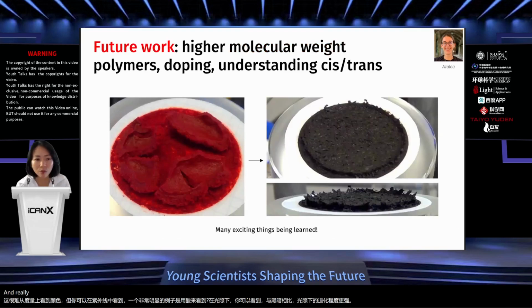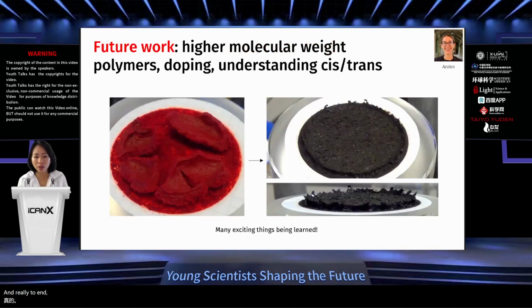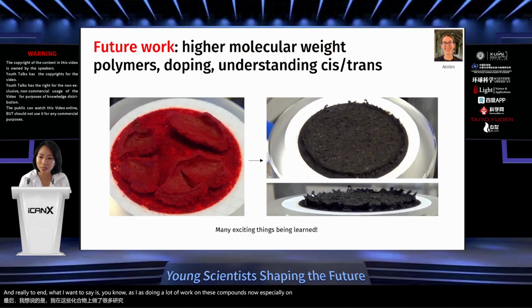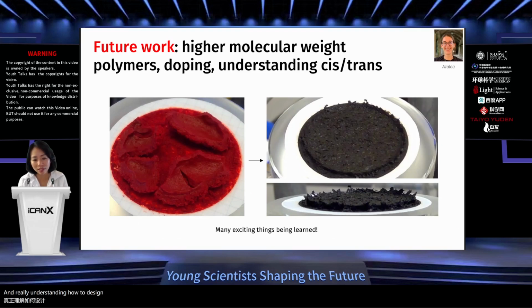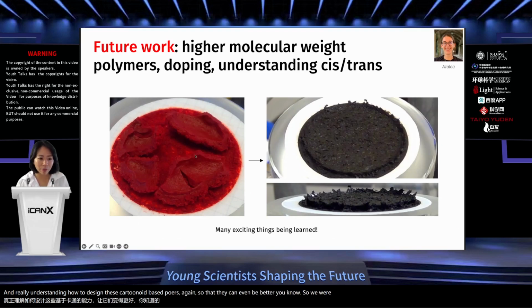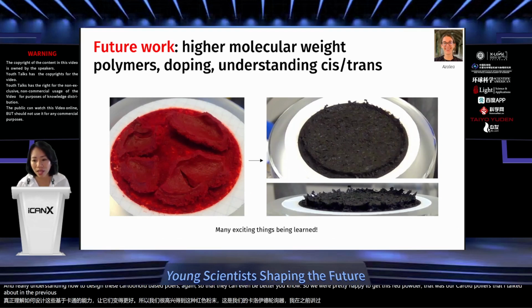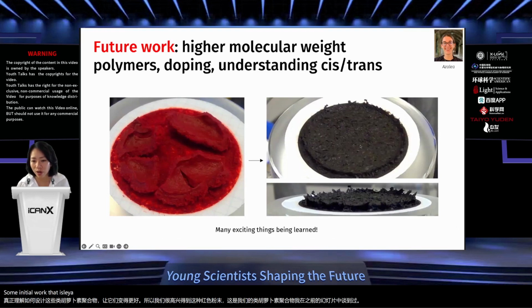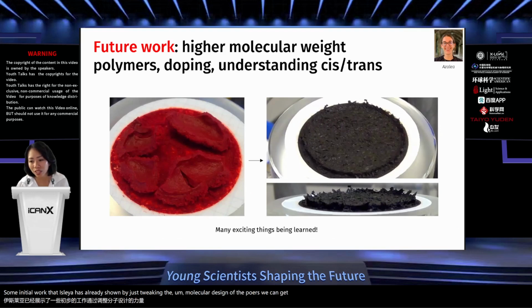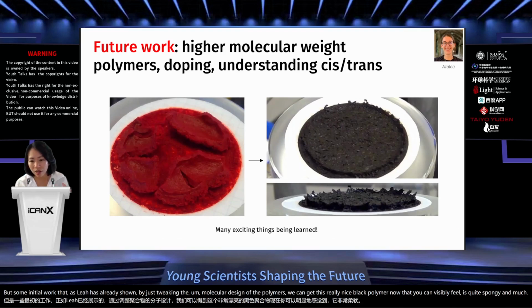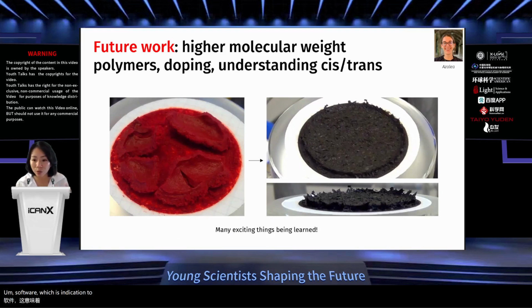And really to end, what I want to say is, Azalea is doing a lot of work on these compounds now, especially on the doping side, which I didn't include today, and really understanding how to design these carotenoid-based polymers so that they can be even better. So we were pretty happy to get this red powder that was our carotenoid polymers that I talked about in the previous slides, but from some initial work that Azalea has already shown by just tweaking the molecular design of the polymers, we can get this really nice black polymer that you can visibly feel is quite spongy and much softer, which is an indication to me that the molecular weight is very high.